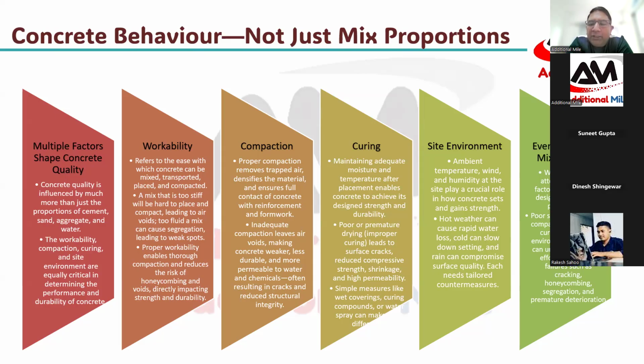Nowadays curing compounds are coming in wax based and water based. Generally, in monsoon, if there is a dry spell, the application of the curing compound should be done in a dry spell. Once it sets and gets dry, especially use wax base where you don't have any coating above it in the future. You can use wax base curing compounds, which will safeguard the structure from rain because of the wax content. Water based needs a drying time, so you must ensure the water based curing compound is applied in a dry spell, and you should give it sufficient drying time. Once it dries, the rain cannot affect it.